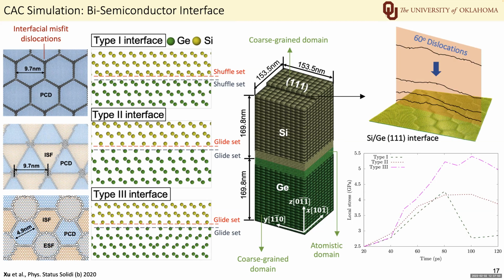We then let a 60-degree mixed type dislocation move towards the interface. We find that the type 3 interface is a stronger barrier to the motion of the dislocation than the other two types. This is because the type 3 interface has the highest misfit dislocation density. This suggests that to have a strong silicon germanium bilayer, we may want to form type 3 interface between the silicon layer and the germanium layer as much as possible.